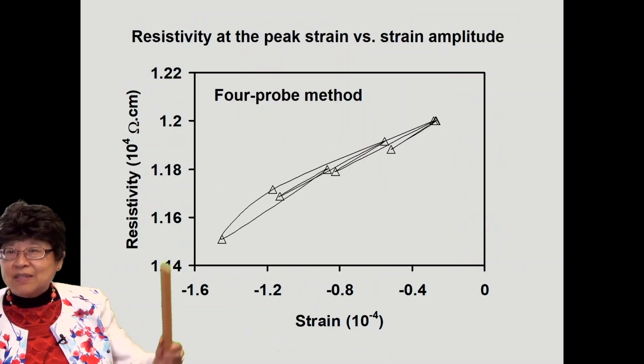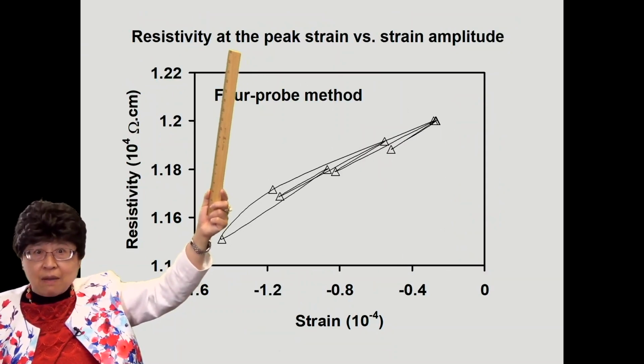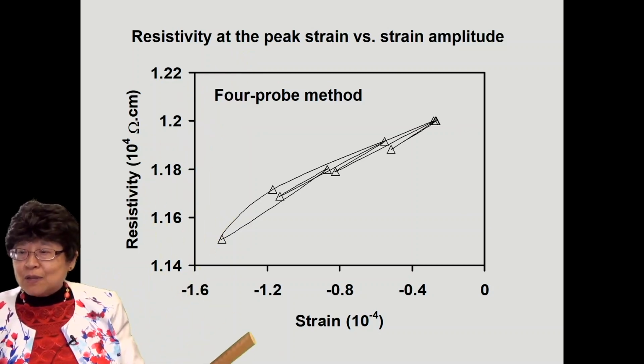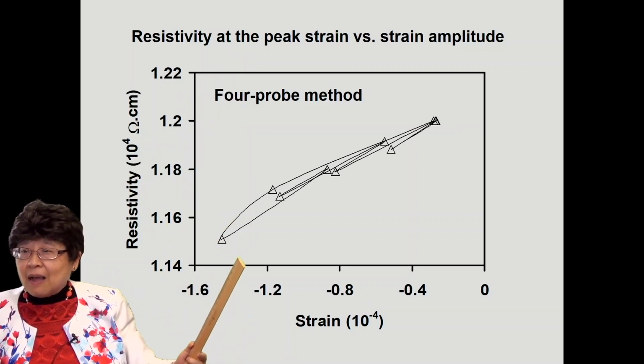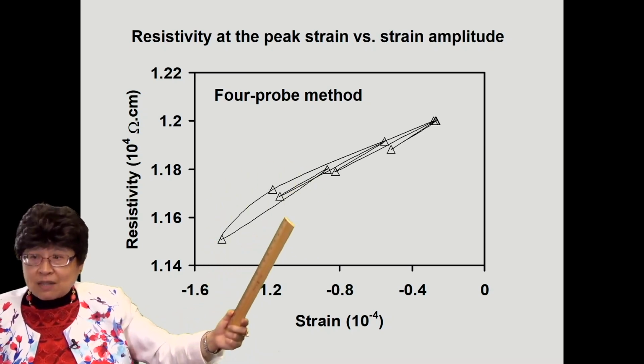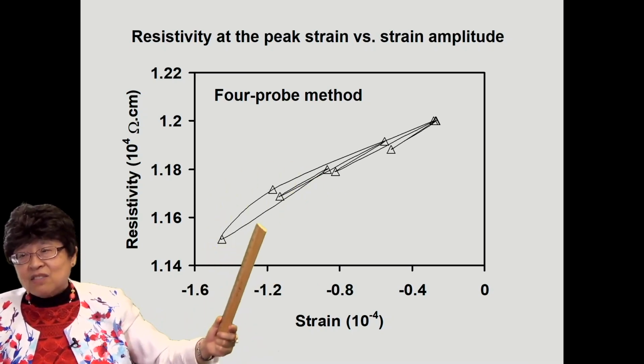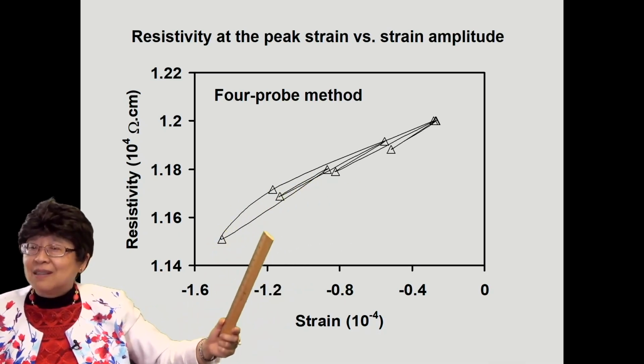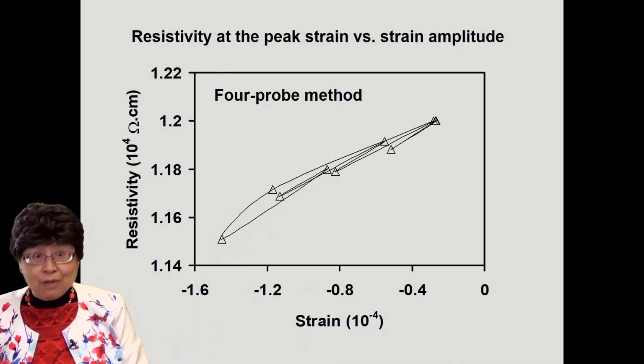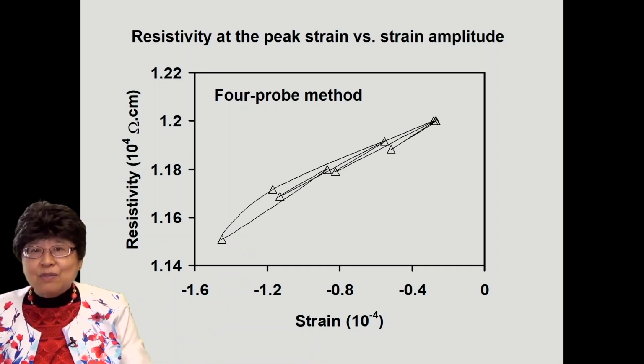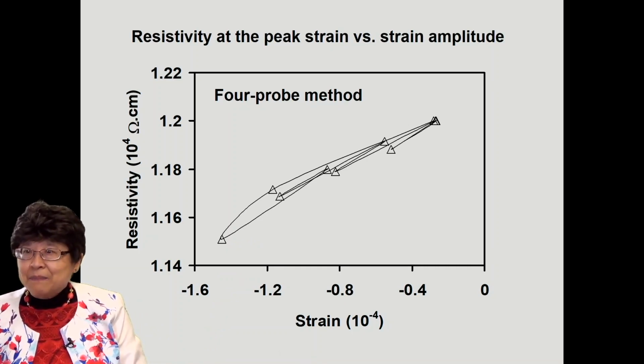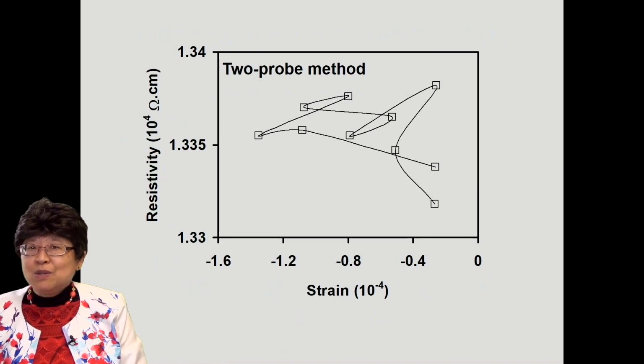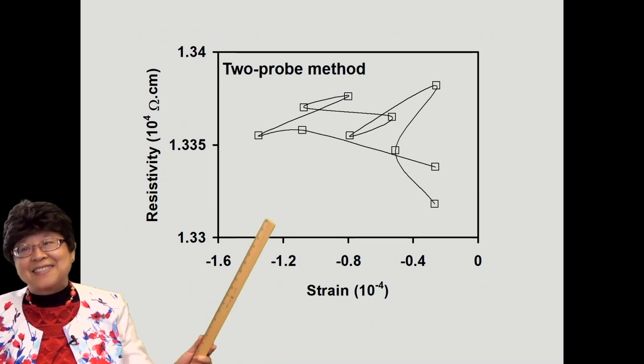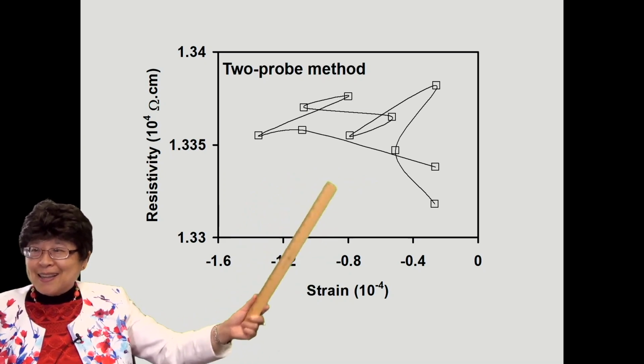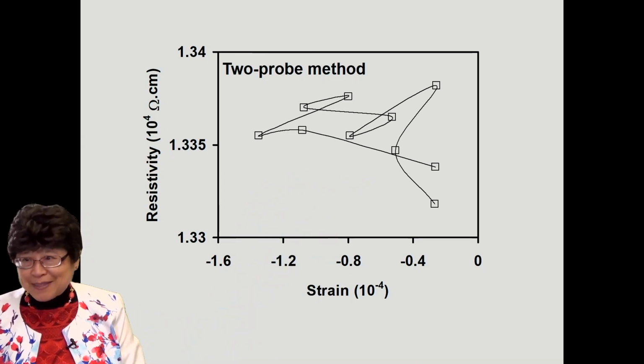Now, one can take the resistivity at the peak strain of each cycle and plot that versus the strain, connecting the points chronologically, and one can see that there's not too much hysteresis. It's more or less linear, and that shows that it really works. The resistivity is responsive to the strain. And this is the result using the 4-probe method. However, if one uses the 2-probe method instead, this is how the data looks. It's terrible. It just doesn't work.